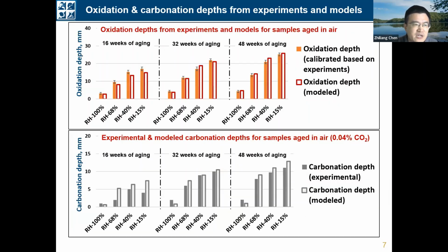And here are some comparisons of the oxidation and carbonation depths from experiments and from models. So at the top are the comparisons for the oxidation depths, and the results at the bottom are the comparisons for the carbonation depths. So as you can see, the modeling results agree pretty well with the experimental results. So that means the aging model that we have developed is well capable of describing the aging processes, including oxidation and carbonation, under different aging conditions.